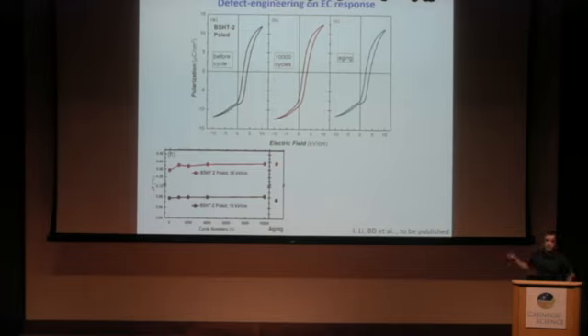But once again, it's a bulk system. If you want to increase the delta T, you have to apply a higher electric field, and the way to have a higher electric field is to make thinner systems. The MLCCs, for instance, multi-layer capacitors, are very nice for this kind of application.